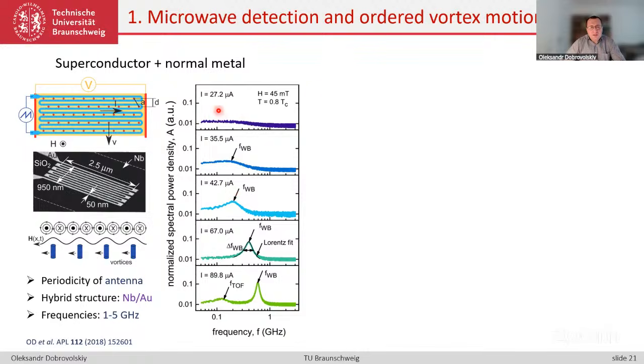And with increasing transport current, there was the appearance of some maxima, some peak, which was detected by the antenna connected to a high frequency oscilloscope, with even two modes observed: a higher frequency mode attributed to the crossing of individual antenna periods, and a low frequency mode related to the full crossing, so the time of flight from this bank to this bank, completely across the antenna structure as a whole.